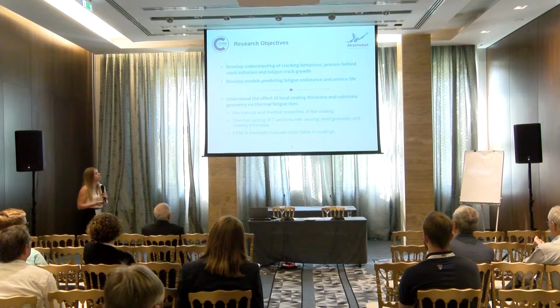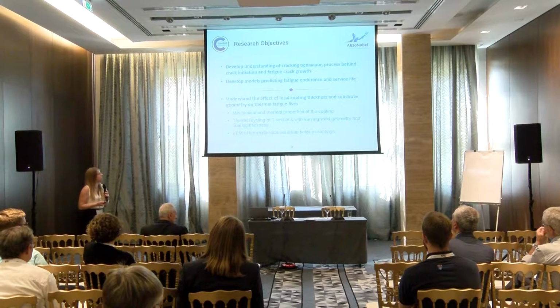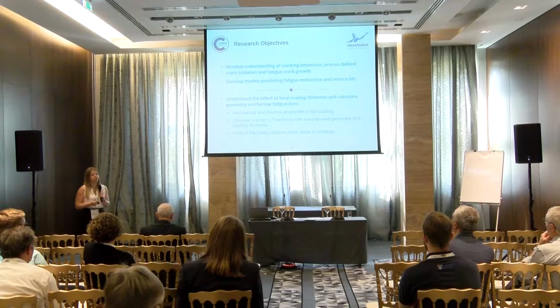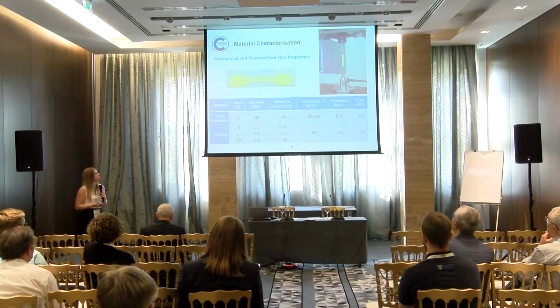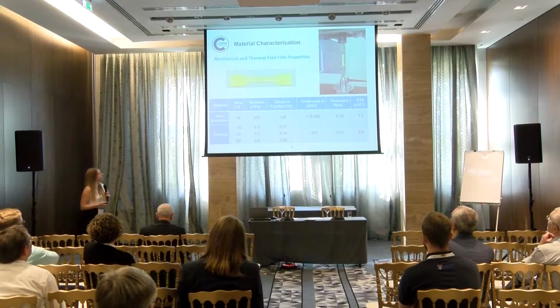In order to do that, a specific highly filled epoxy coating was chosen. Its mechanical and thermal properties were determined. It was then subjected to thermal fatigue cycles. And finally, finite element modelling techniques were employed in order to understand the strain fields that would develop within the coating.